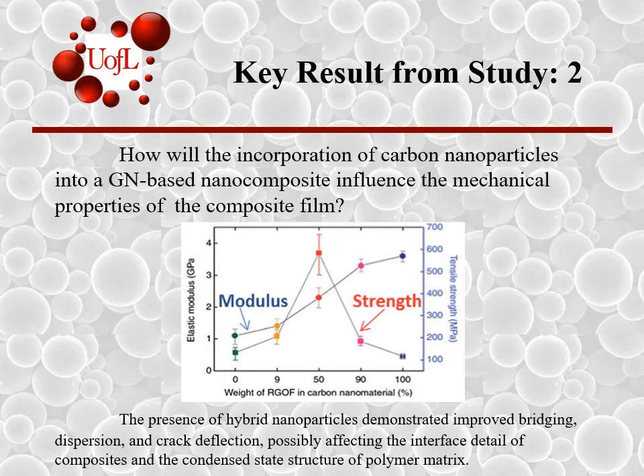Another study reviewed in this paper aimed to answer how the incorporation of carbon nanoparticles into a graphene nanosheet-based nanocomposite influences the mechanical properties of the composite film. The figure below displays the Young's modulus and strength of finished composite films at varying percent weight of reduced graphene oxide film, RGOF, and then carbon nanomaterial. The graph shows that as the percent weight of RGOF and the carbon nanomaterial increases, the Young's modulus increases, but the strength peaked at 50% RGOF.